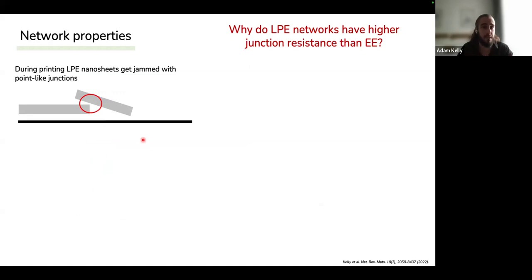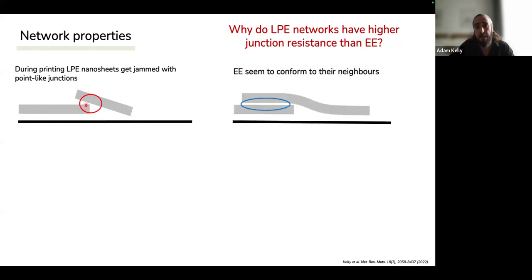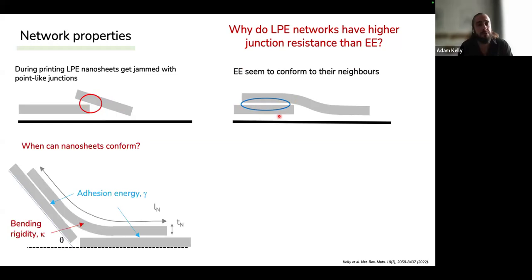Well, the reason is, as I showed you in the SEMs, the LPE nanosheets tend to get jammed together. They don't sit on top of each other very well, and you get these point-like junctions. Because the electrochemically exfoliated nanosheets are quite thin, they're able to conform very easily to each other, and we get these nice interfaces. And the way to understand this is, when is this possible? Well, we can take a simple model system with parameters like the length of the nanosheet, the thickness of the nanosheet, the adhesion energy, and the bending rigidity, and then some arbitrary bending angle.